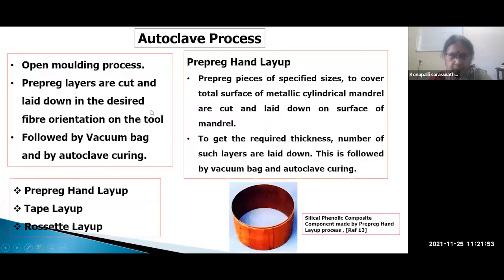Then autoclave, because it is an open molded process. Then pre-preg layers are cut, laid down in the desired fiber orientation on the tool, and then it is followed by vacuum bag and putting in autoclave and curing under temperature, pressure, and vacuum.